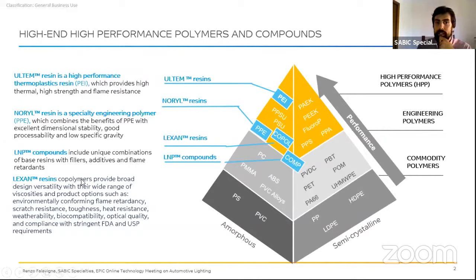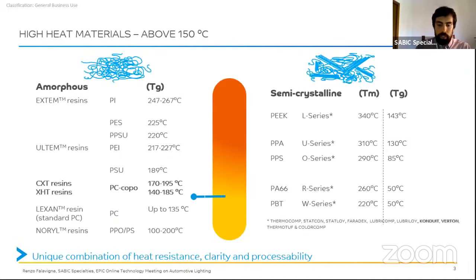And then we have our Lexan resins that you most probably know. In the specialty side of SABIC, we sell and promote Lexan copolymers, so copolymers of polycarbonate. What can we offer for the automotive lighting applications? Well, let me focus a little bit on a couple of products. I already mentioned polycarbonate copolymers. So here you can see a couple of them, Lexan CXT and Lexan XHT. Those are copolymers where one of the monomers of the polycarbonate has been substituted with another monomer. And this change leads to an increase of the Tg, glass transition of the polycarbonate. Playing a little bit with the chemistry, because we are synthesizing those resins, we can increase the Tg up to 190 degrees C.